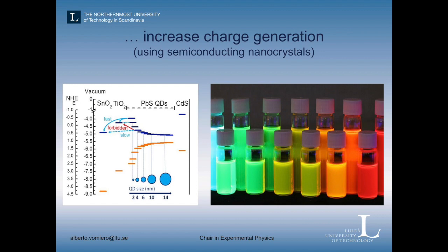These are quantum dots, which are very small particles between, let's say, 2 to 9 nanometers, which have very interesting optical properties. You can see here, you can tune the color of these particles by simply tuning their size. So you change the size and you change the color, which is very important because it means that you can absorb the sunlight in different parts of the solar spectrum just by changing the size of your particle, which is not particularly demanding from the technical point of view.